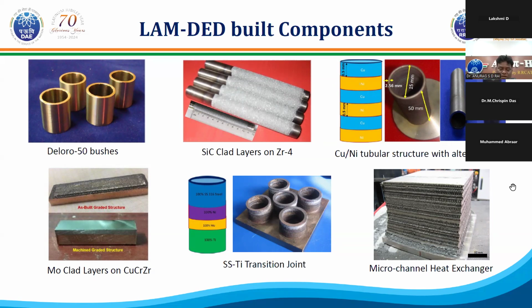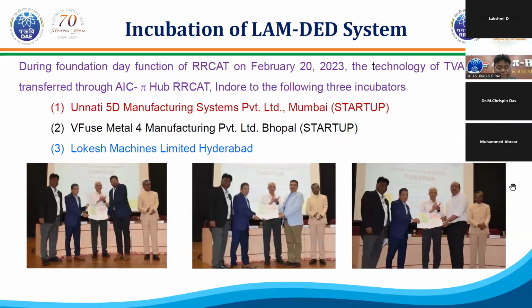Now it looks simple, but the typical deposition rate we get is in the range of 6 to 8 or maybe 10 gram per minute, and you have to deposit, say for example, maybe 50 kg, so you can understand how much time we take to build such a big volume. But it is doable, and we are doing a lot of things in this direction.